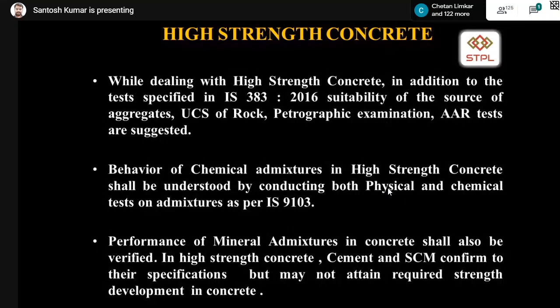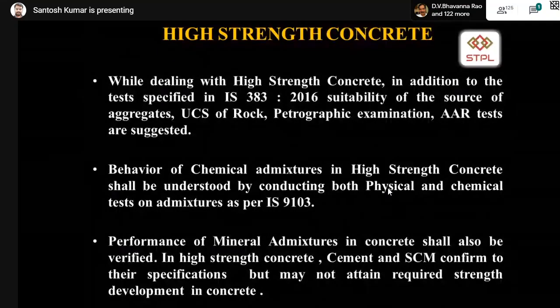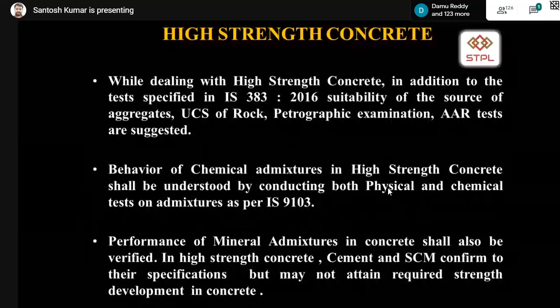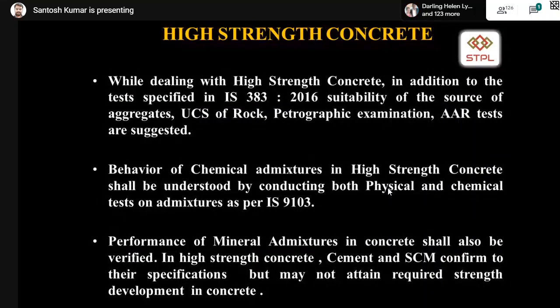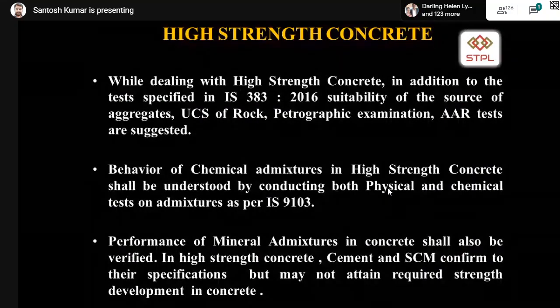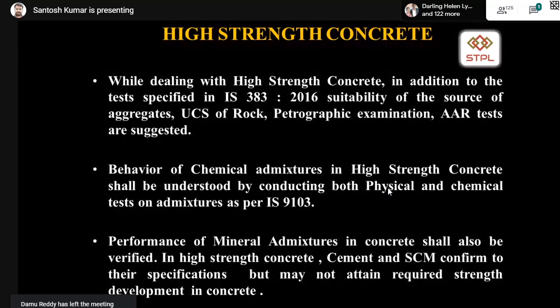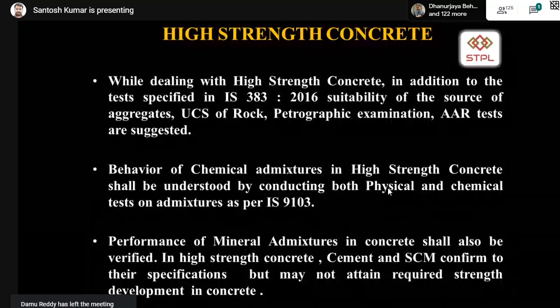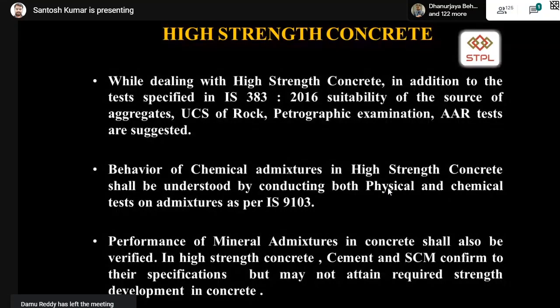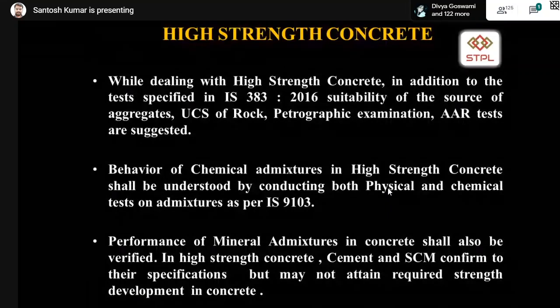In high strength concrete, cement and supplementary cementitious material, for example fly ash and GGBS, may conform to their specifications, but they may not attain required strength development in high strength concrete. It is a practical problem which we face when we design high strength concrete. Your cement may give 65 MPa at the end of 28 days. Your fly ash comparative strength may be more than 85%, but when you mix in high strength concrete, there is no result.